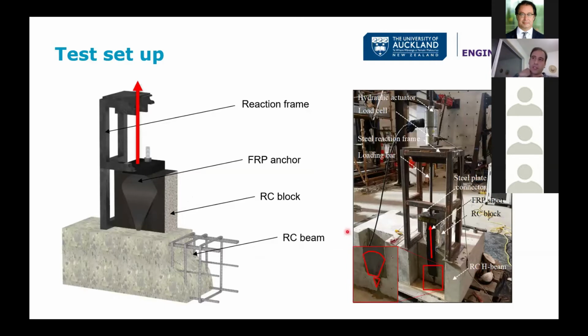It is similar to the shear strengthening of a beam that we saw in the first slide, but upside down. So that beam at the bottom is the slab, where we have the anchor introduced. Then we have a concrete block at the top, which is the beam, and these two are not connected. Then we have the sheet wrapped around the block and the FRP bonded to the sheet and then introduced into the beam. And without spending too much time, because I don't have a lot of time, I basically lifted this block vertically until the fibers broke in there, and I recorded the load. This is for straight anchors. On the right hand side, for bent anchors, it's a similar approach, just the anchor is bent into this block rather than straight.